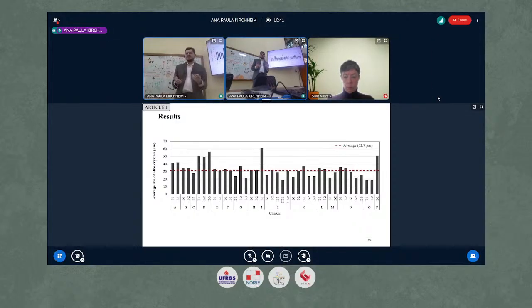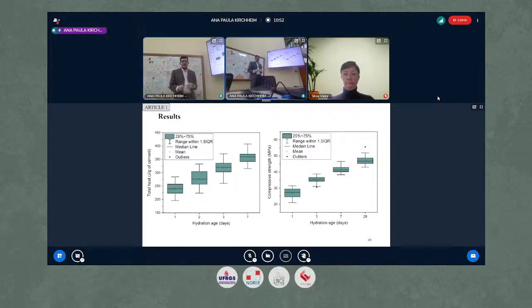Here is the alite average crystal size, which also varies a lot, obtained by optical microscopy. And here we see a variation from 20 micrometers to 60 micrometers. According to the textbook of Taylor, a good alite crystal size would be below 25 micrometers. Here we have the results of heat release and compressive strength. We also see a great variation among the clinkers.